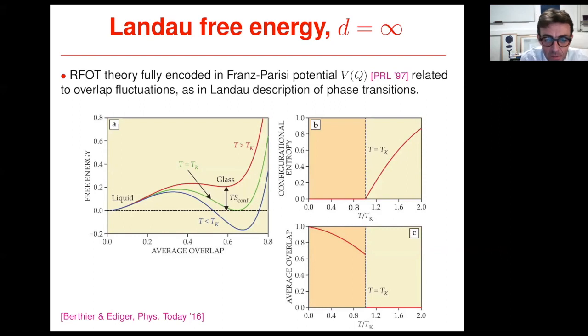So it's such a good order parameter that it's possible to rephrase the mean field theory of the glass transition in the language of conventional phase transitions, expressing, for instance, the free energy as a function of the overlap, just as in conventional Landau descriptions of phase transition. So this is what I'm showing you in this plot here. And this Landau free energy in the context of glass physics has received the name of the Franz-Parisi potential V of Q. Okay, so the behavior of this free energy as a function of the order parameter is shown here for a specific mean field glass model.